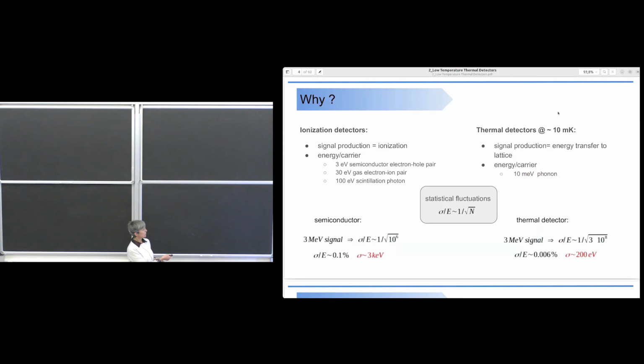If you take a semiconductor, that is the best solution among ionization detectors, for a 3 MeV signal you get a resolution of, say, 3 keV, or if you prefer, 1 per mil energy resolution. And this is only the intrinsic energy resolution that can be achieved using this mechanism of signal production.